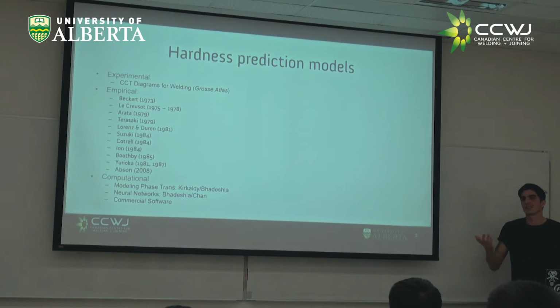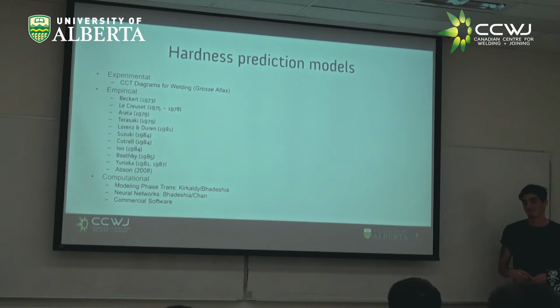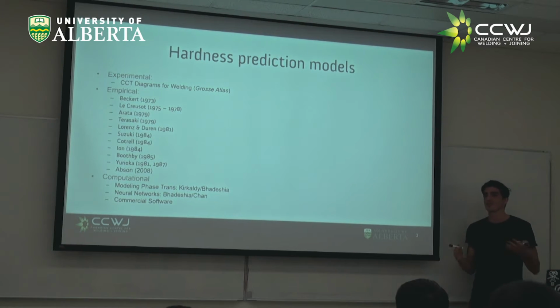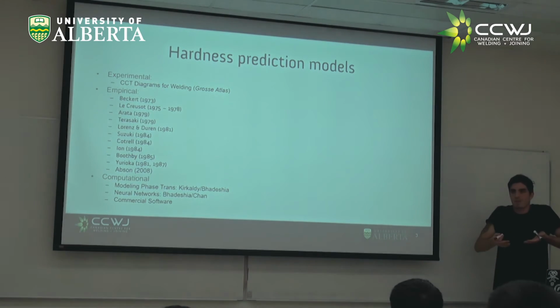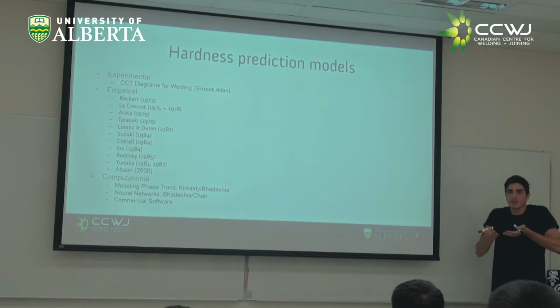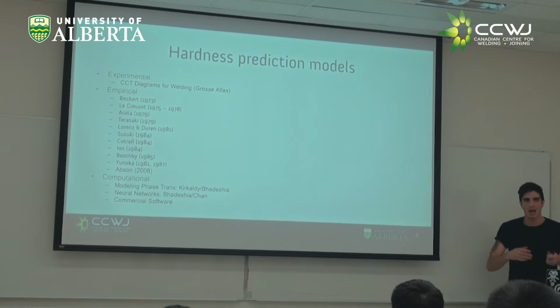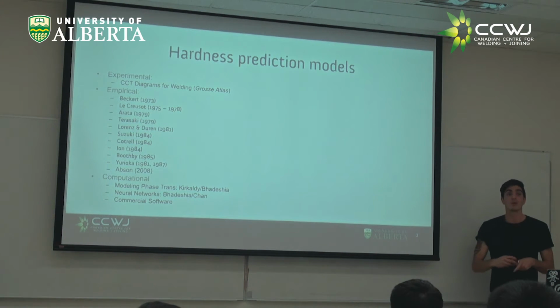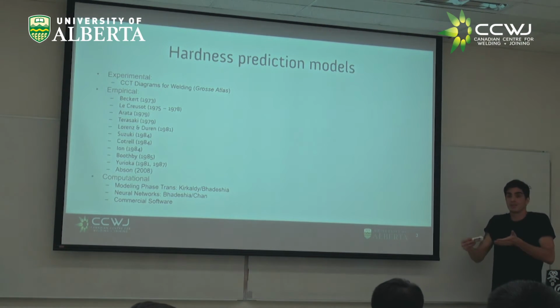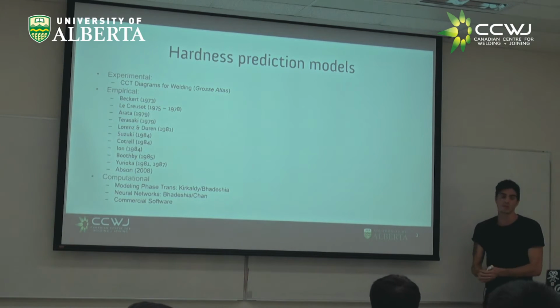Well, the process is a heat treatment. So, exactly, the temperature. For a heat treatment, you don't want the austenite to grow. That's the whole point of making a good heat treatment. You heat it up to the minimum temperature you need, plus 50 Celsius if you want, and that's how you make a heat treatment. You don't go up to 1400 Celsius and then cool down, because you're going to have a more hardenable material, and that's something that you want to avoid, right?